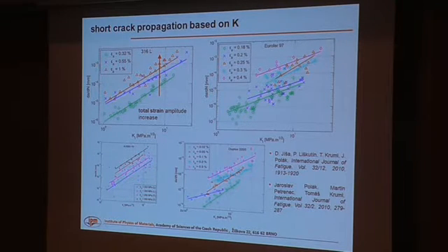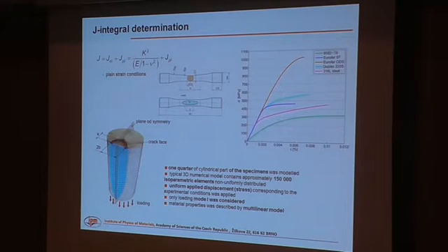And that's because here, for these loading conditions, linear elasticity fails, and it's necessary to also include the plastic part of deformation in front of the crack tip. So we use the J integral to describe behavior of these small cracks, and therefore it was necessary to do some